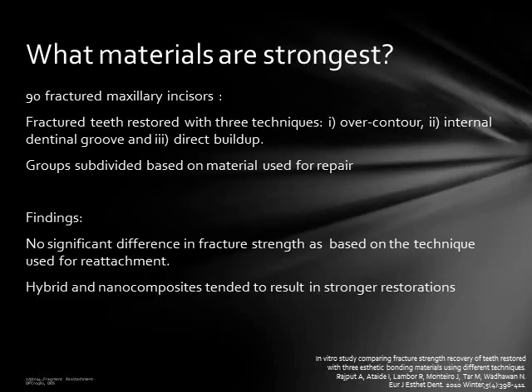The other interesting finding is that the reattachment restorations and the direct composite restorations were comparable in fracture strength. Again, giving us a procedure that is potentially faster, likely to have better aesthetic results, and without a compromise in strength.